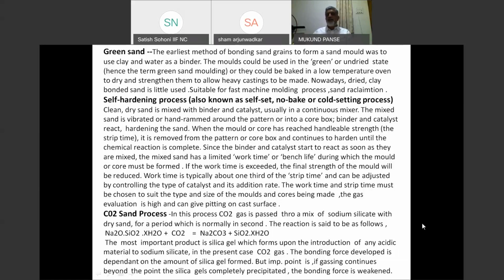Then again, you cannot strip the pattern immediately, as the sand has to develop sufficient strength to retain the shape. So the setting time is called strip time. The work time and strip time of the sand can be changed depending on which catalyst you are using, or by changing the addition of the catalyst, like fast setting, slow setting, or quantity. Suppose a small jobbing foundry makes castings from 500 kg to 5 ton. The molding box size will vary, the time required to make the mold will vary, and all these variations in sand properties are required. But most of the current continuous sand mixers have these facilities and can be used conveniently.